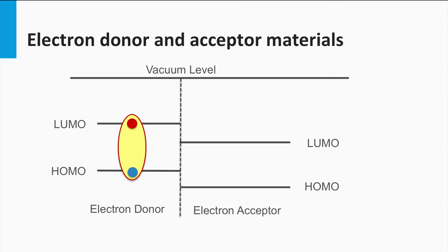In organic materials this is not the case. Light excitation results in so-called excitons, which are excited electron and hole pairs, which are still bound and strained due to the mutual Coulombic force between the particles. The exciton can diffuse through the material. These excitons have a low lifetime in organic materials. They recombine back to the ground state within a few nanoseconds, meaning that the diffusion length of such excitons is in the order of only 10 nm.